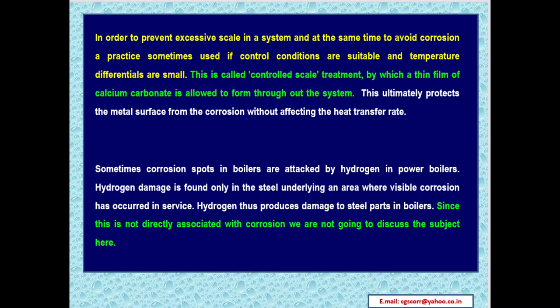In order to prevent excessive scale in a system, and at the same time to avoid corrosion, a practice is sometimes used if control conditions are suitable and temperature differentials are small. This is called controlled scale treatment, by which a thin film of calcium carbonate is allowed to form throughout the system. This ultimately protects the metal surface from corrosion without affecting the heat transfer rate.